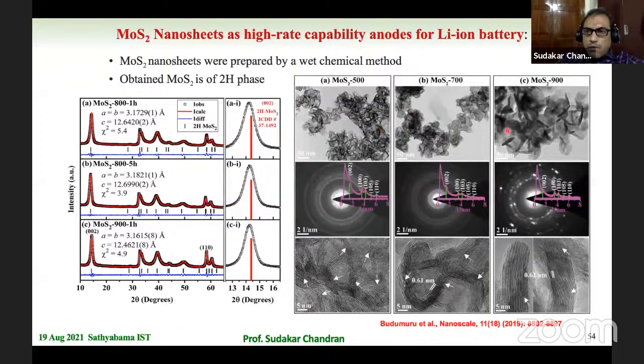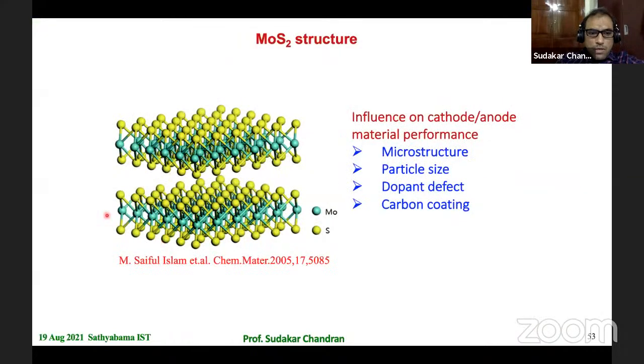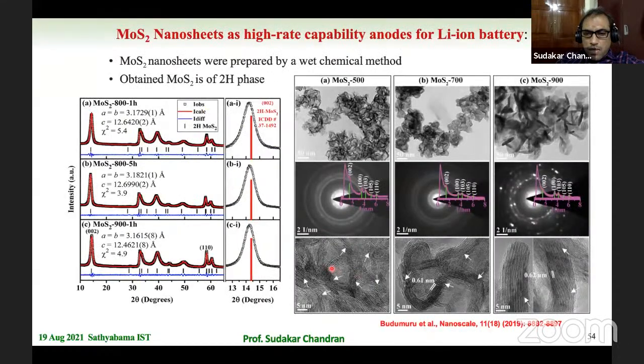As you can see here, depending on the annealing temperature, the moly sulfide nanosheet looks very different. In fact, in the high resolution image you can see very few layers of moly disulfide. Each line you see here is nothing but one layer. Each of these layers is a bit disordered, curved, with lots of defects, and these defects minimize as you anneal them at a larger annealing temperature, and the number of layers also grows. So in one way, we can control the defects and number of layers in these sulfides.